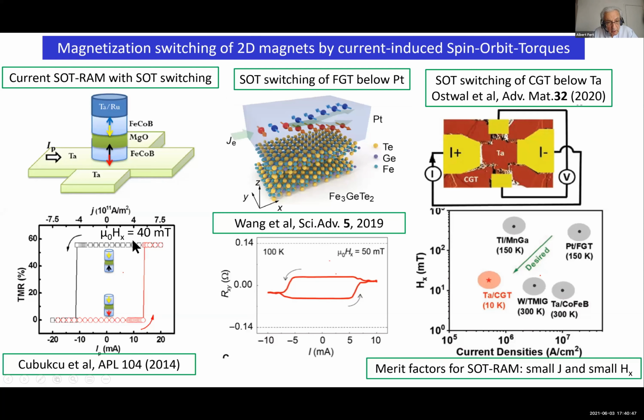So you can see an example of experimental results for this type of structure, where by injecting a current you can reverse the magnetization of the bottom layer here, from down to up, and then by reversing the field, you can reverse it in the opposite direction. Of course, as I have said before, this is obtained in general by also applying an additional in-plane field along the direction of the current, the x direction.